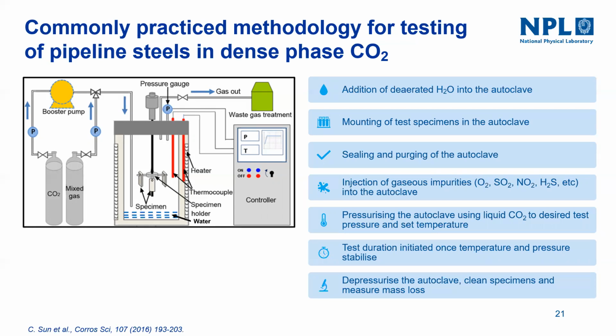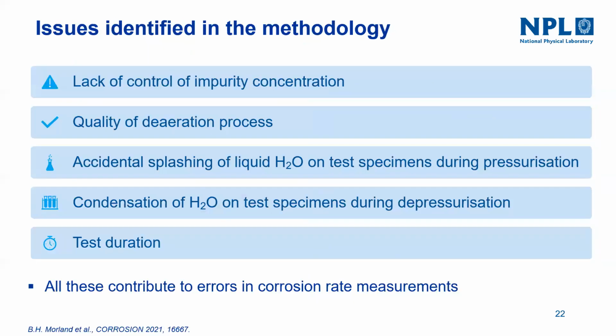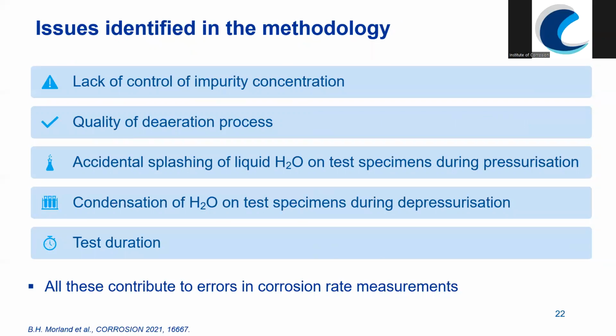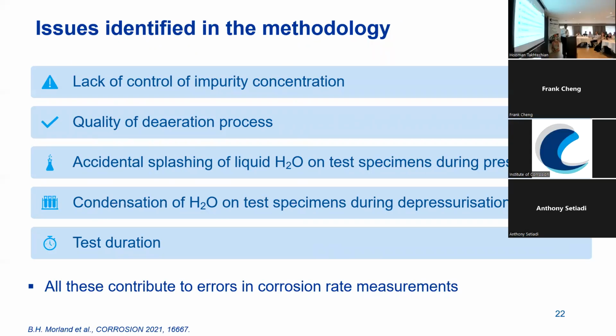And after the test procedure, depressurize the autoclave, clean the specimens and measure the mass loss. This is the majority of the studies; almost 90% have followed this methodology in the past decade. So significantly, there are several issues. One thing is the control of the concentration of impurities, which is lacking because the concentration of impurities is not measured during the testing. It is measured prior to putting into the autoclave.